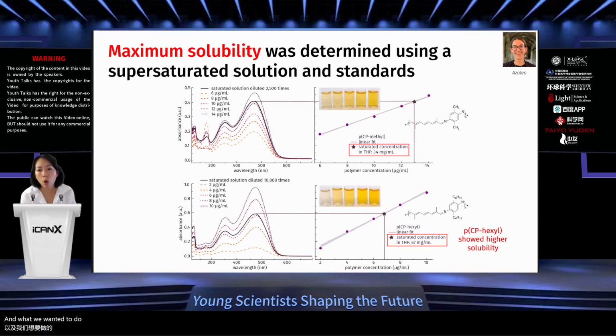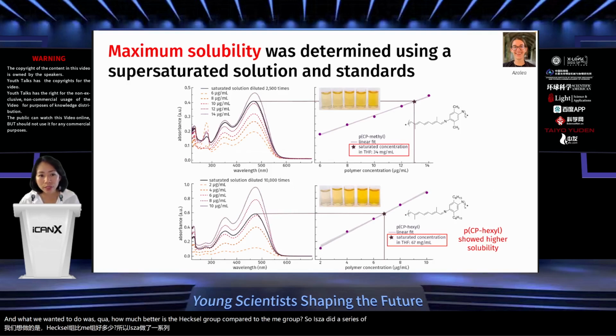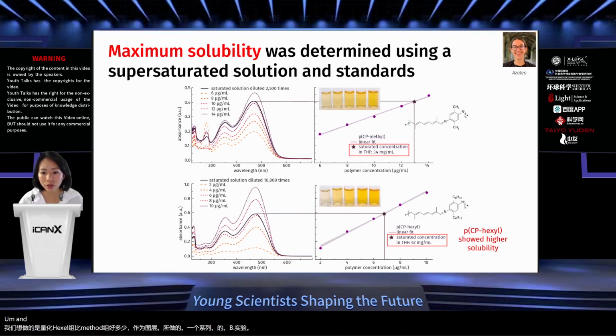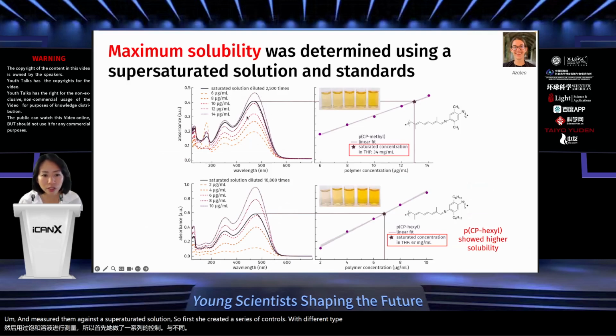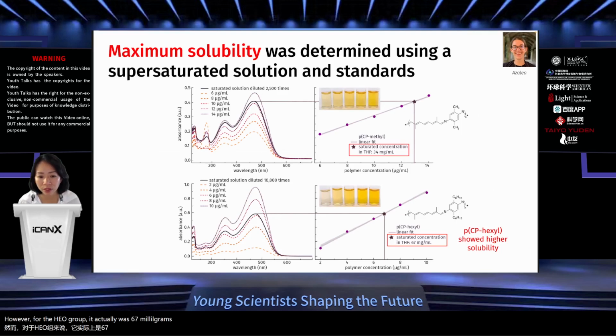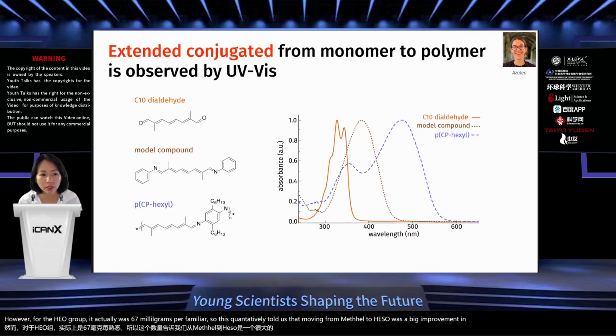And what we wanted to do was quantitate how much better the hexyl group is compared to the methyl group. So Azalea did a series of UV-vis experiments and measured them against a supersaturated solution. First, she created a series of controls with different concentrations, created the supersaturated solution, and to figure out what it was, she just diluted it until it fell within the range of the standards. And she can back calculate that the saturated concentration of the methyl group is actually 34 milligrams per milliliter. However, for the hexyl group, it was 67 milligrams per milliliter. So this quantitatively told us that moving from methyl to hexyl was a big improvement in solubility.